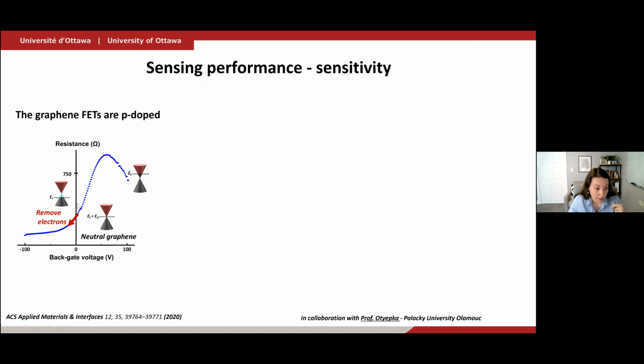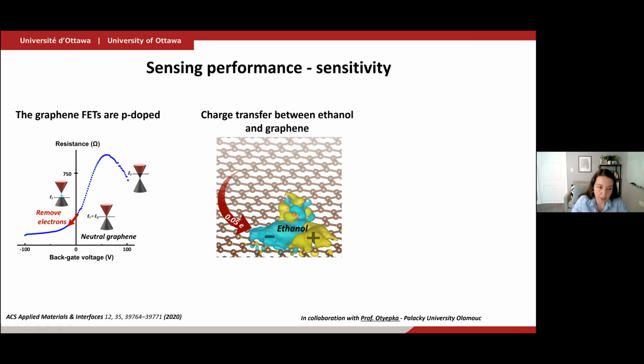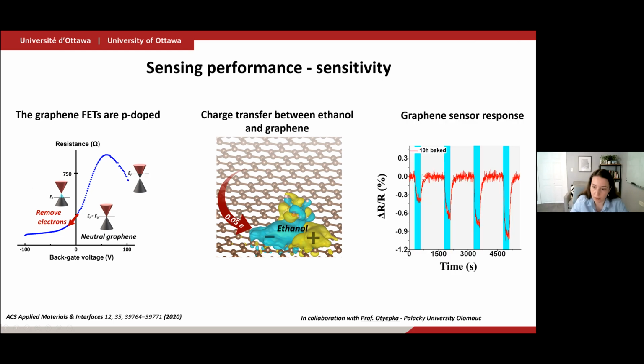So in this case, for example, our graphene field effect transistors start off by being p-doped. And that has to do with the type of residues and nanofabrication that we do on the surface. And as they start out being p-doped, if you have a molecule now that will remove further electrons from the graphene surface, you'll essentially become even more p-doped, and so your resistance will go down. So that is one of the possible sensing mechanisms in these type of graphene sensors.